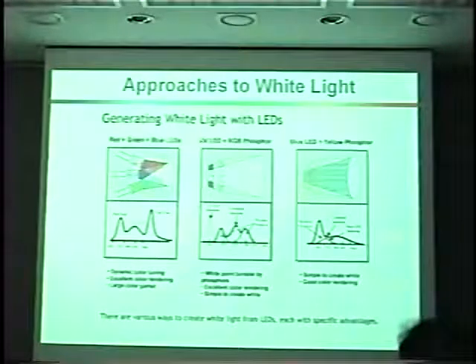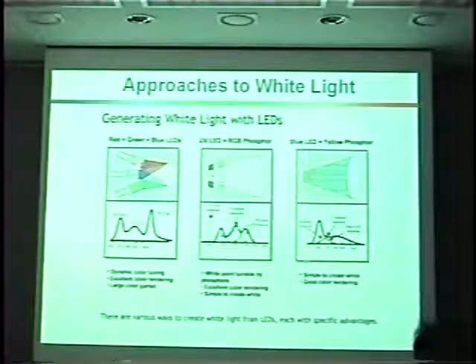A common approach, over here on the right-hand side, is to take a blue LED, which is gallium nitride based, and on top of it put a yellow phosphor, a broad emitting yellow phosphor, which combined with the blue emission will give you a fairly good white light. Most of the white LEDs that you probably see now have a little blue tint to them. They're being made with this particular approach here.